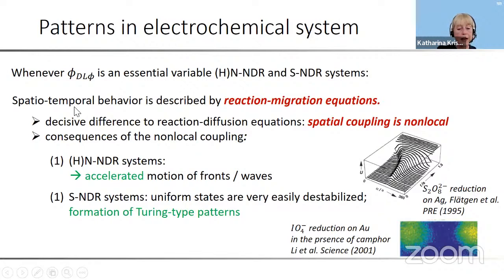To obtain the correct formulation for the electrode potential for the spatially extended electrode, you have to solve the Laplace equation within the electrolyte with boundary conditions on the counter electrode or far away, where you assume an equipotential curve. And then you have your pattern in phi dl at the electrode, because phi dl is our autocatalytic variable. If we expect patterns, you should have some variations of the electrode potential lateral to the electrode. And this would be the second boundary condition for the Laplace equation. The other ones you can choose as zero flux boundary conditions.